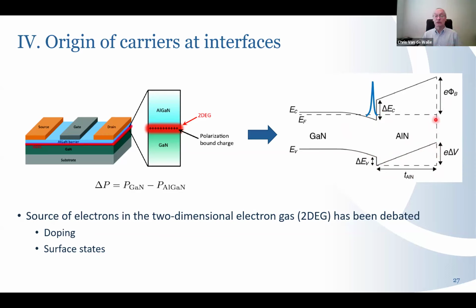However, starting some years ago already, including in work done at Cornell, it was pointed out that there is a problem with this way of looking at things, namely the density of surface states is not high enough to be consistent with this explanation. The density of electrons in the two-dimensional electron gas can be, I'm just saying something, close to 1 times 10 to the 13th per square centimeter.